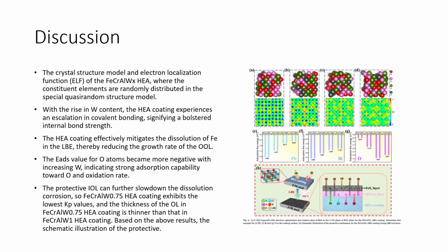So we move to the discussion from this paper. The crystal structure model of the electron localization function, ELF, of the material, where the constituent elements are randomly distributed into the special quasi-random structure model. With the raised tungsten content, the coating experienced an escalation in covalent bonding, signifying a bolstered internal bond strength. The coating effectively mitigates the dissolution of Fe in the LBE, thereby reducing the growth of the outer oxide layer. The Eads value for O atoms became more negative with increasing tungsten, indicating strong absorption capability toward oxygen and oxidation rates.